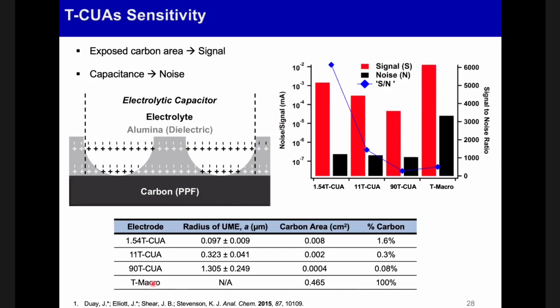So we've actually done detection of hydrogen peroxide and nitric oxide on these electrodes. Nitric oxide is particularly interesting because it's produced by your immune cells in defense to pathogenic infections. And for that, we needed to further modify the electrode with gold nanoparticles to increase the electrocatalytic activity. And we needed to apply on top of it a cellulose acetate membrane with a pore size of about 6 angstroms that basically filters out all these other biological species and is really selective for just nitric oxide.